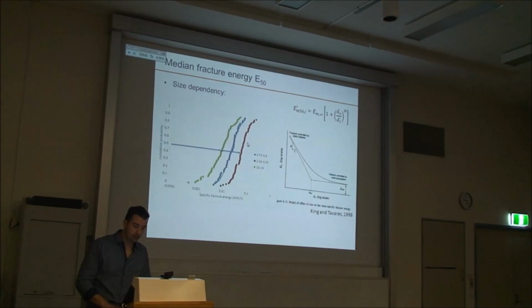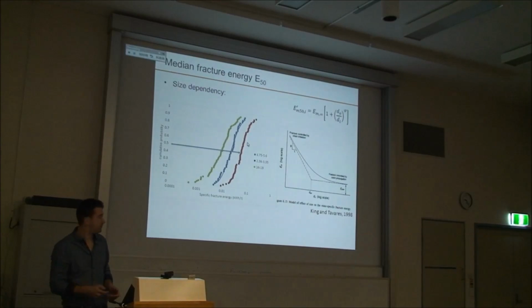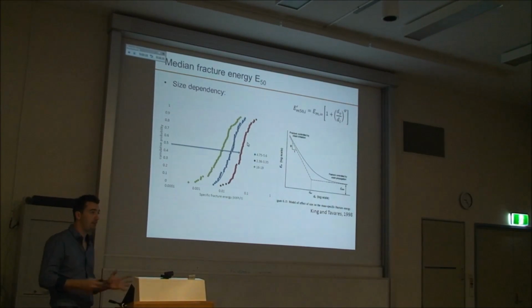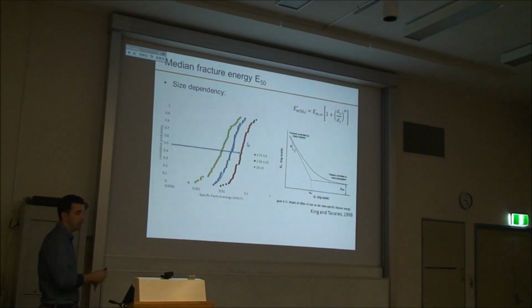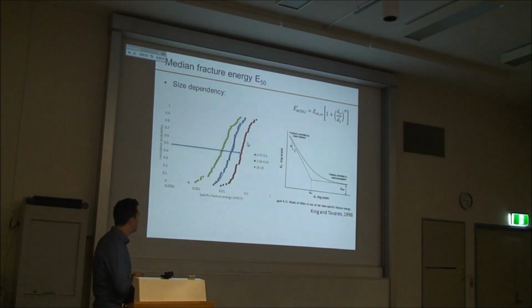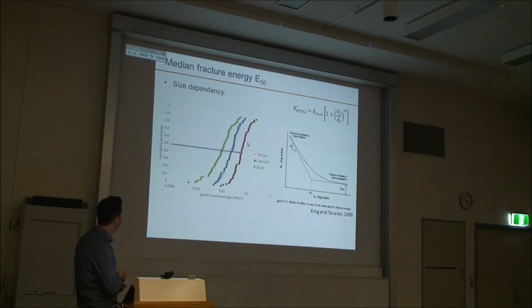And then you do that. So this sample was one size fraction. We do different size fractions. You can see here the same sample, but plotted for 3 different size fractions. And you can observe that they have different average, E50, and different variability, or geometrical variance of the distribution. And what was shown here about the team in Utah and Marcelo is the relationship between the E50, this value, versus size.